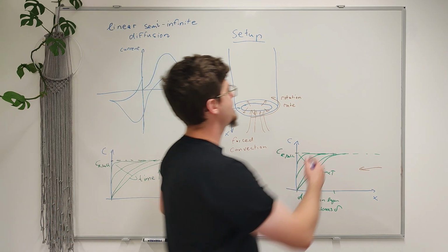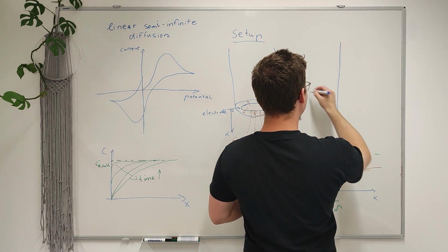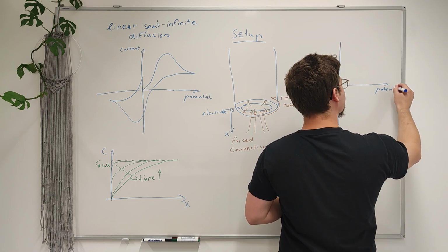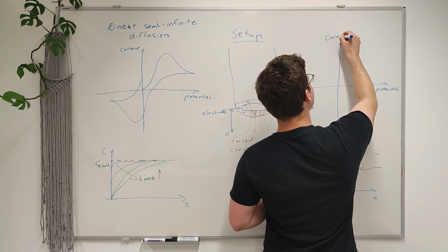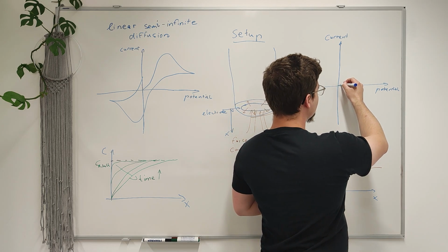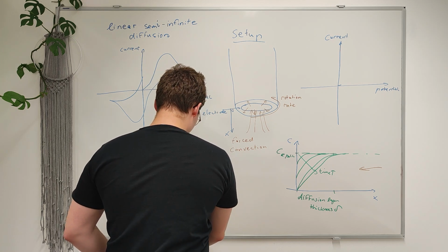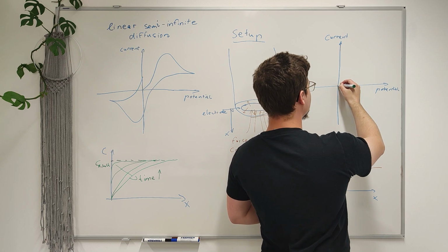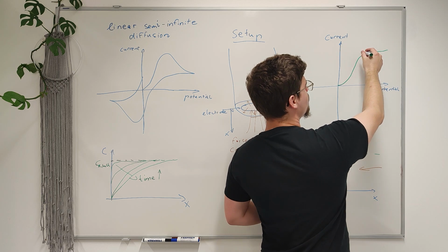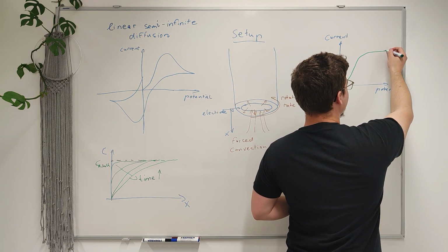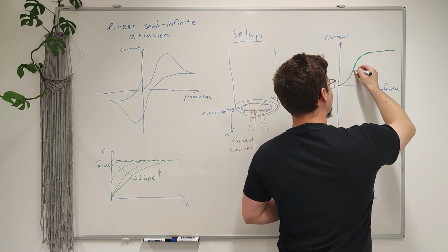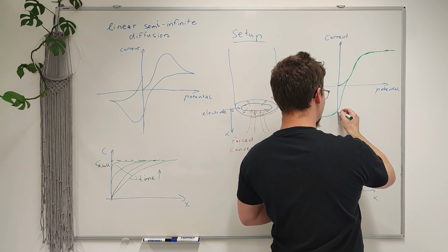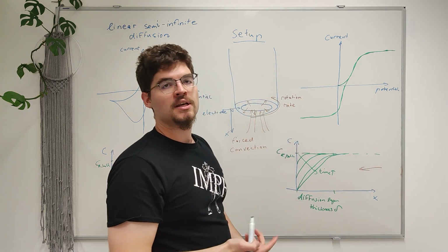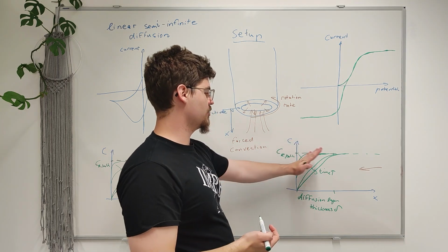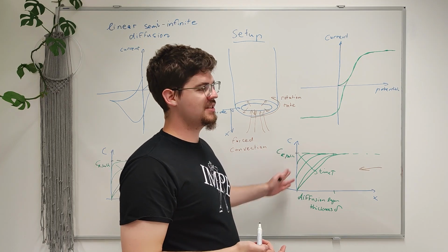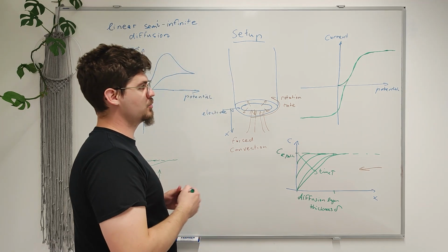And for our cyclic voltammogram, let's sketch what this means. We again plot current over potential. For this case, let me plot this initially with green for this rotation rate. Instead of a peak that would appear here in the condition of linear semi-infinite diffusion, we run into a current plateau. And in the reverse scan, we get a similar plateau here. Now in this case, I've sketched this for the reduced species. Of course, for the oxidized species, you can also plot such a concentration profile, where if the concentration of the reduced species decreases, the concentration of the oxidized species increases, and so everything is vice versa.